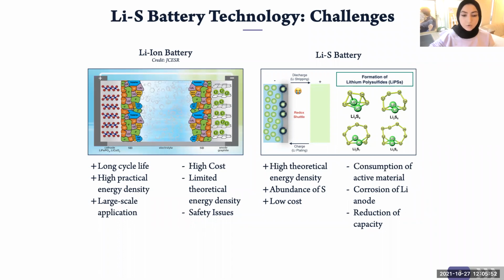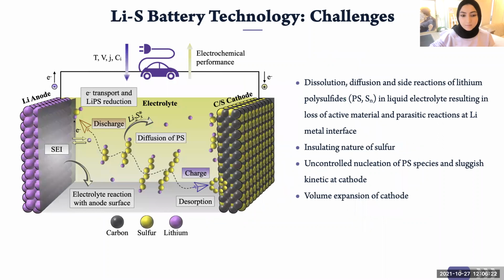But the widespread commercialization of lithium-sulfur is still hindered by a series of problems. Lithium participates in parasitic reactions with the dissolved polysulfide species from the cathode, leading to the formation of lithium polysulfides, which then travel to the anode and coat it. And this happens during every cycle, making the battery work less and less efficiently until it eventually dies. This is a schematic diagram showing the process where the cyclo-octasulfur ring on the cathode is opened during the discharge process and reduced to Li2S8, which is then converted to shorter chain polysulfide species that are soluble in the electrolyte, and they travel to the anode and insulate it. And consequences of this process include direct capacity fading of the battery, high self-discharge rate, and decrease in Coulombic efficiency.